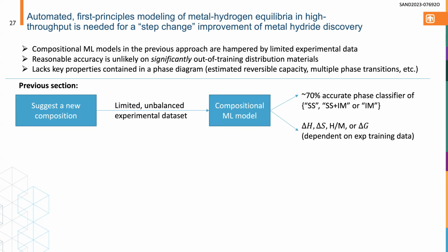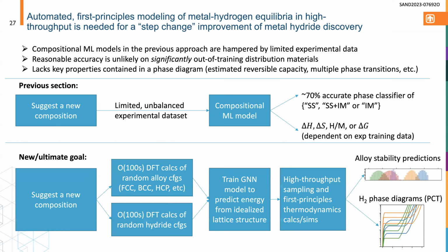So previously, we just suggested a composition, looked at the compositional model, and used that to predict phase stability and these thermodynamic properties at a coarse level. But the new approach would really want to be able to suggest a composition, and through DFT be able to predict the phase stability of that particular composition as a solid solution in these different lattice types, and then also probe the hydrogen absorption energy landscape. And if you can put both of those together and predict both of those with a graph neural network model, for example, you could actually, through high throughput sampling, come up with a more first principles, not only alloy stability prediction, but actually regenerate the hydrogen PCT curves.